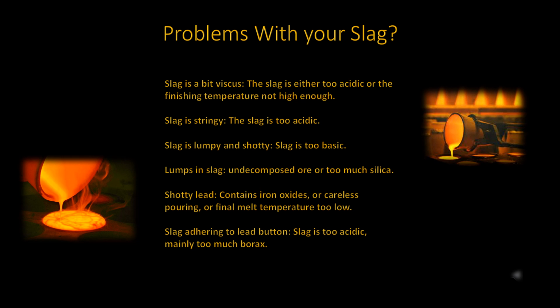Once cooled, when the button is broken from the slag and some slag adheres to the button, it indicates that the slag was too acidic, mainly too much borax. An increase in a basic flux or a decrease in the acidic flux would be the intended fix.